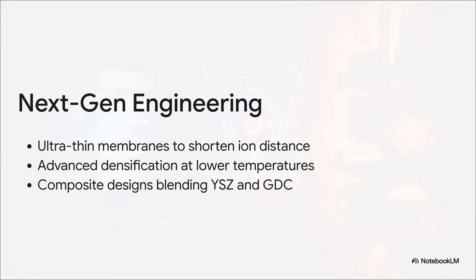So, to bypass YSZ's physical limitations, engineers are deploying some truly cutting-edge interventions. First, they're pushing tape casting to its absolute limits to create ultra-thin membranes. This physically shortens the distance ions have to travel, which naturally lowers resistance. Second, they're exploring advanced densification techniques, like spark plasma sintering, to achieve perfect density at much lower manufacturing temperatures. And third, they are designing these ingenious composite, multi-layered sandwiches that blend the rock-solid stability of YSZ with the high conductivity of materials like GDC.